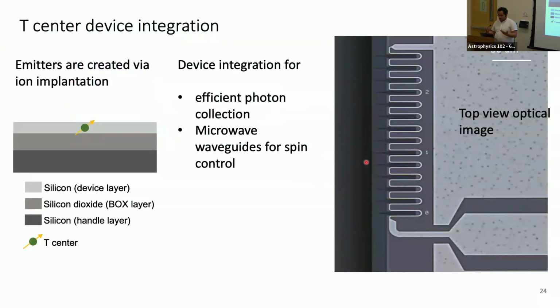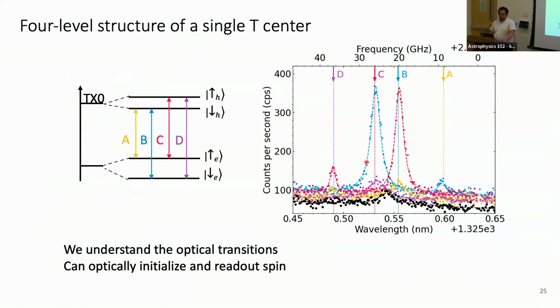In order to do spin control, in addition to our photonics platform, we also added some microwave circuits. It's a superconducting niobium transmission line, such that we can effectively deliver microwave pulses to our spins. And we've done two-laser spectroscopy. We can observe all these four transitions. We can identify the g factors and the Zeeman splittings in the ground state and the excited state. When we pump on one of these transitions alone, it goes dark. We pump to a dark state. So if you're doing just optical experiments, you need to repump, just like you do in atomic physics and so on.